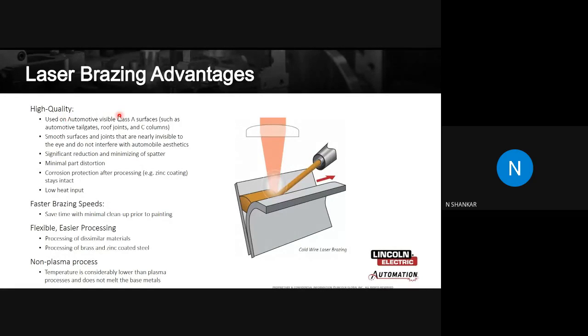I told you it's used on automotive visible class A surfaces. What it means is parts that are visible externally: the tail gates, the roofs, the C columns. All of these are more or less 100% built with the laser brazing process all across the globe. It's got very, very low heat input, absolutely no distortion, and makes sure that you get strong weld joints. They do very high-speed welding. The productivity, which is a concern for the automotive industry, is handled here, and it's a very flexible process. And of course, it's a non-plasma process. That is one more advantage of laser brazing.